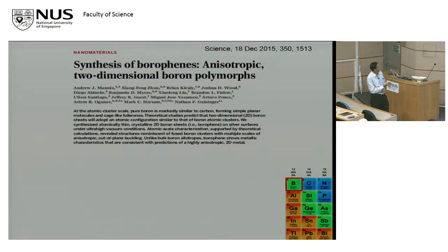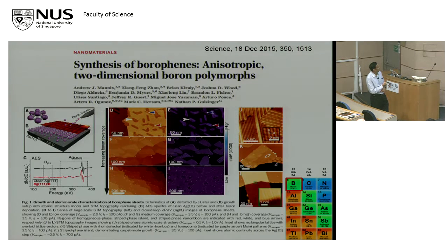There's a recent paper in Science on borophene, boron polytypes, by the Northwestern group. So again, they demonstrated growing from a boron source on silver 111. Again, it's on a surface to stabilize it. So they show all these crystals, measured its properties, and as I said, fairly straightforward work, but published in a high-impact journal because they used the story of a new two-dimensional material. Okay, so this is one way of getting published in these journals if you're interested.